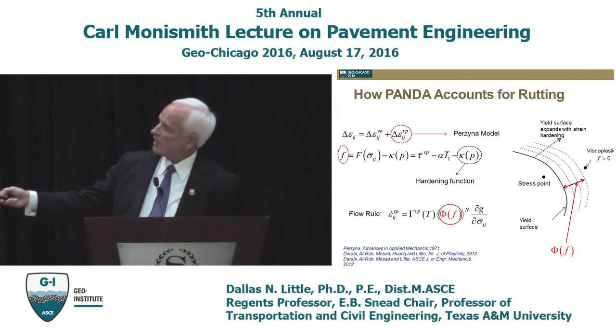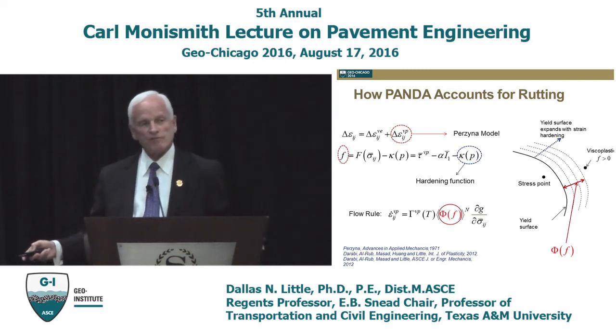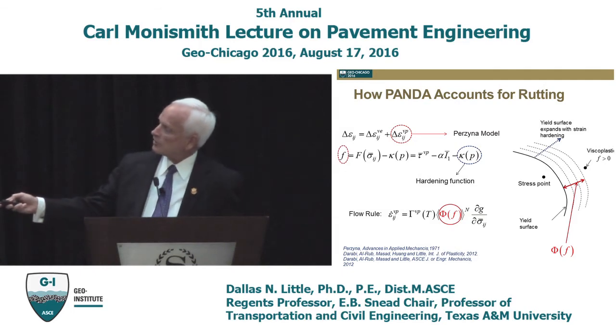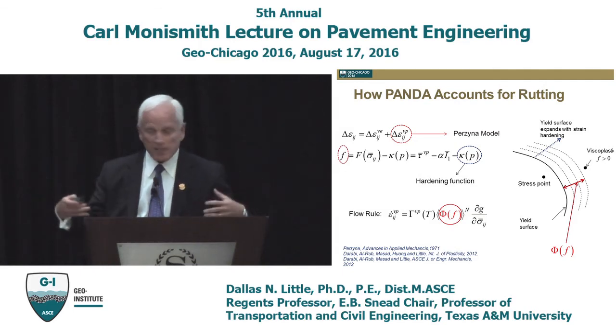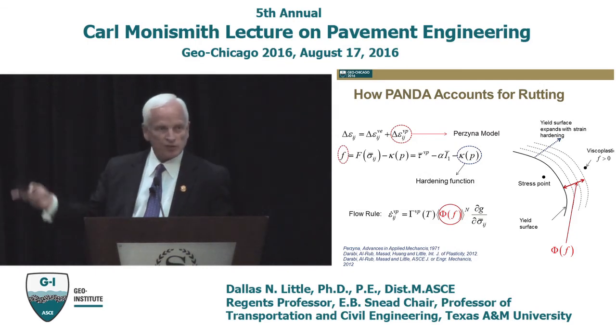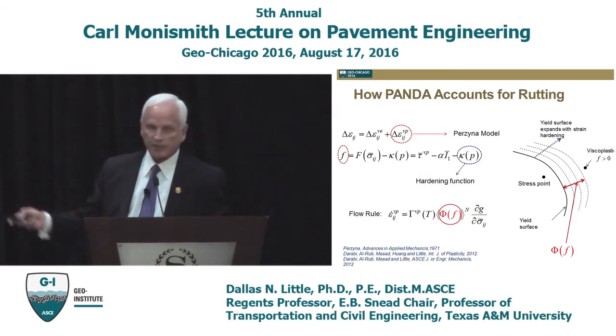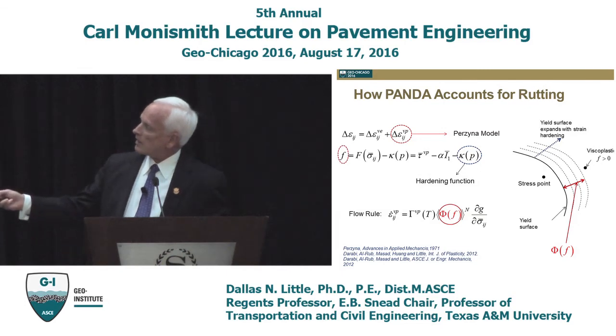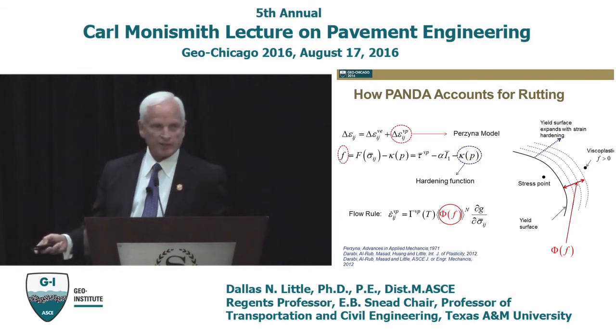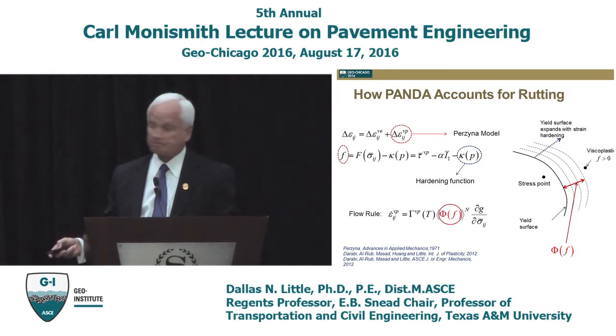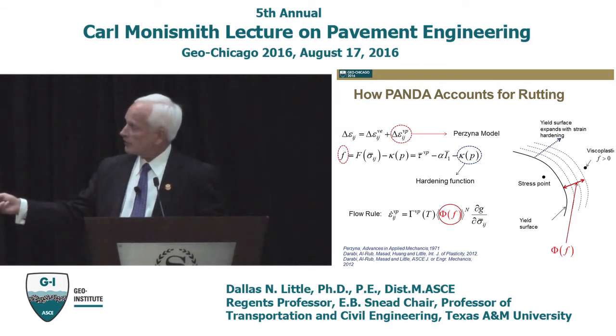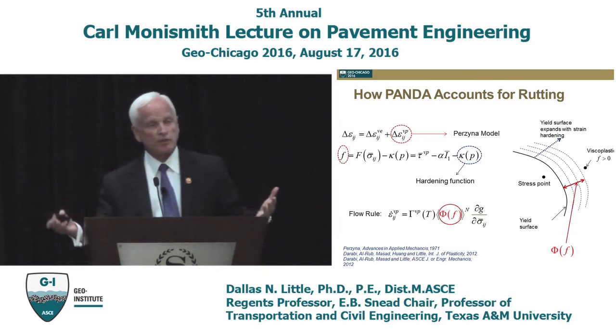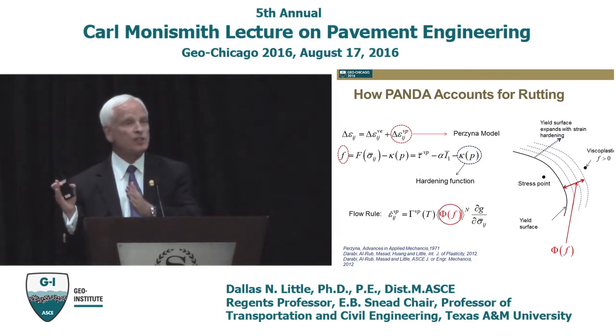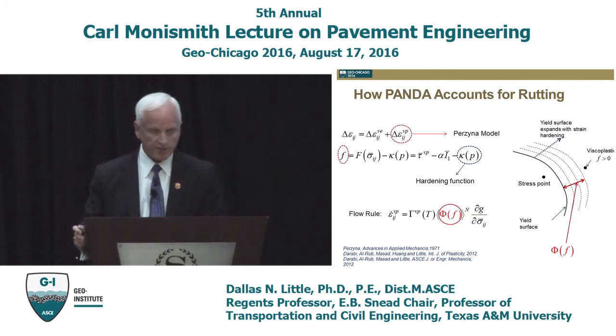something that is a function of a shear stress, the I sub 1 first invariant, which is the confining pressure, times alpha, which is the internal friction, so that's a Drucker-Prager type relationship. And it's modified by the hardening function out here, the kappa sub P. So that defines the yield surface, and it is a dynamic yield surface, which hardens with loading, and with long-term relaxation between loads, there's a bit of softening that can occur. Dynamic yield surface.